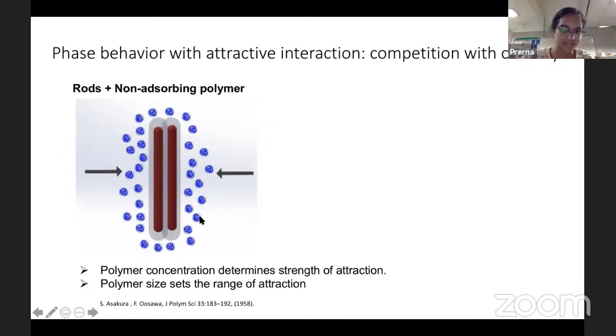Now this interaction is highly directional because you should think of these spheres getting excluded from the hard rods. Essentially, hard particles cannot interpenetrate each other. So this gray zone around the red rod indicates the area within which the center of mass of the polymer coil cannot enter. If you have two such rods that come close enough such that their gray zones overlap, then excluded volume will decrease and some free volume will become available for the polymer coils. As we said, the phases with highest entropy will be the phases of equilibrium. That tells you that the equilibrium structure for this will be for the rods to come together.